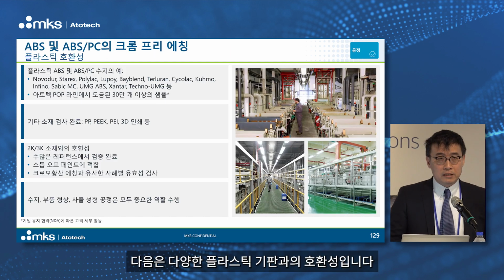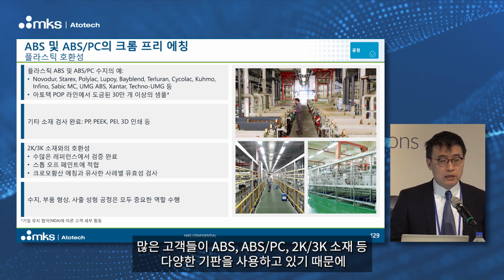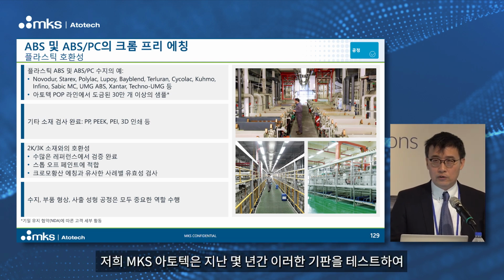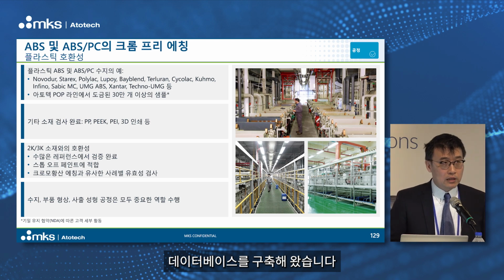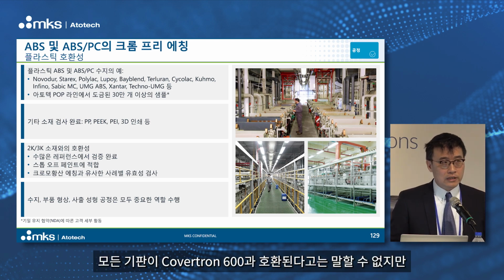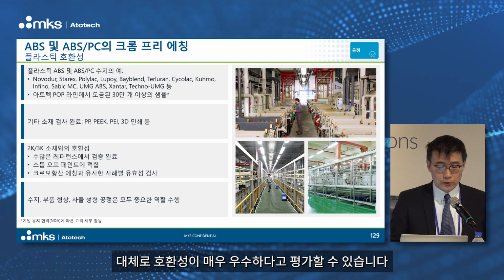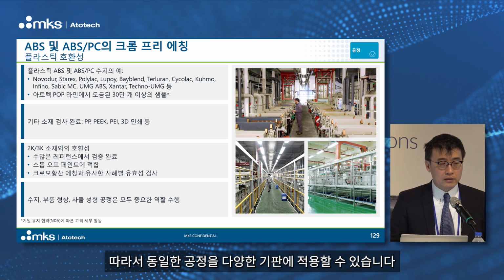This is about the compatibility with different plastic substrates, because many of our customers are using different substrates in their production, like ABS, ABS-PC, or even 2K, 3K materials. We have been testing that for a few years now, and we've created a database of different substrates. I cannot say that every substrate we can do with Covertron 600, but I think the compatibility is quite good, and we can use the same process for different substrates.